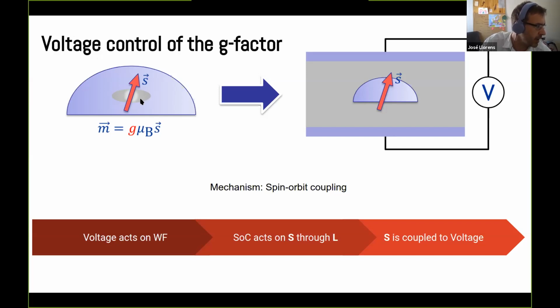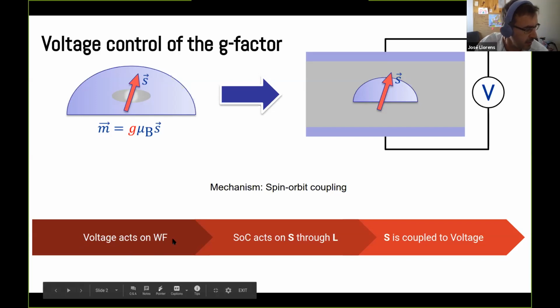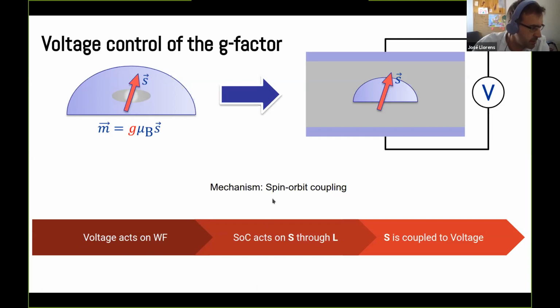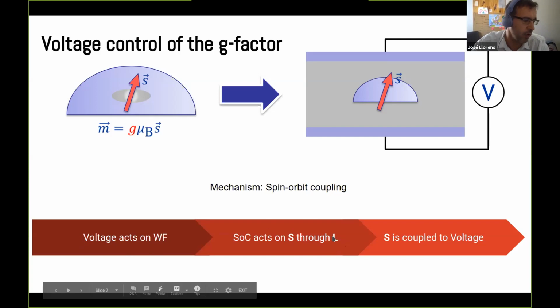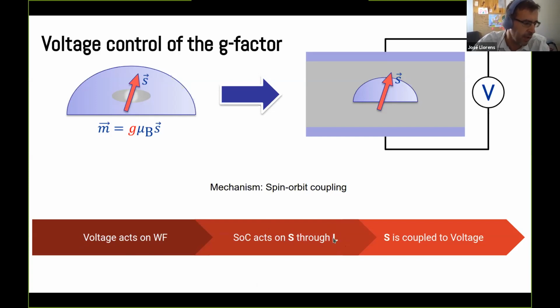If we have, for example, an electron confined inside a quantum dot that has a spin, this spin is insensitive to the voltage, but its dipolar magnetic moment is proportional to the spin through this g factor, and this g factor depends on the wave function of the electron. So it's possible that by applying a voltage we modify the wave function and also the spin. Basically, the voltage acts on the wave function through the quantum confined Stark effect. The spin-orbit coupling couples the spin to the orbital angular momentum or, in general, orbital degrees of freedom. And through this coupling, we have, in an effective way, coupled the voltage to the spin.